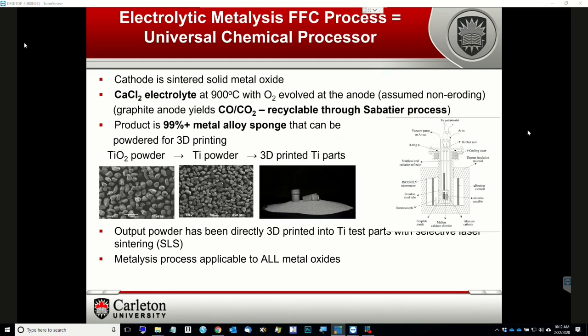One slight problem with the technique is that the anode is constructed from graphite. Now this reacts with the oxygen evolved at the anode to yield carbon monoxide and carbon dioxide. However, this can be recycled through the Sabatier process quite readily.